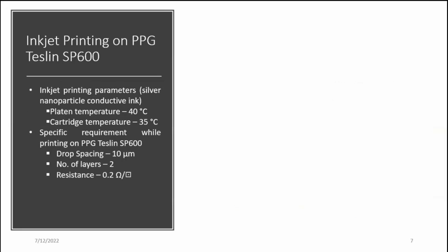Now for inkjet printing on Teslin SP600, we need to first optimize the parameters of the inkjet printer because no one has reported inkjet printing on Teslin SP600. So we went through a critical observation. I have chosen platen temperature as 40 degrees C and cartridge temperature as 35 degrees C, while we require drop spacing 10 micron, and we need to print 2 layers. As I have previously mentioned, Teslin is a pretty porous material. So then we get the resistance as 0.2 ohm per square. I'll discuss a little bit about it. When we were using shape memory polymer, the drop diameter was approximately 75 micrometer.